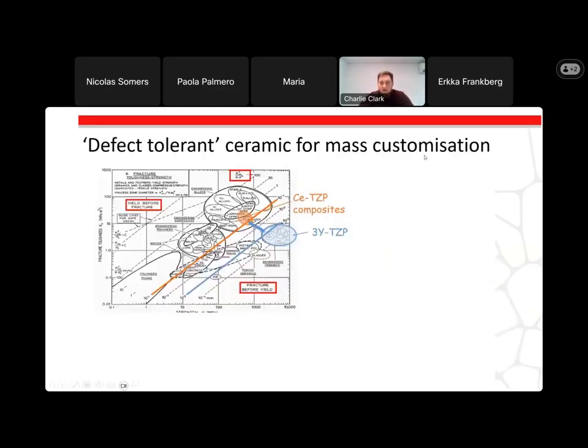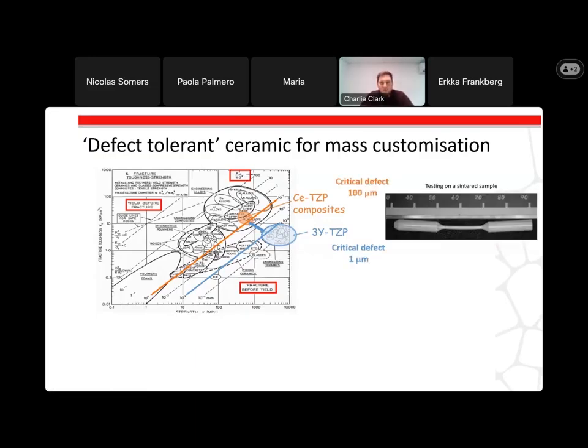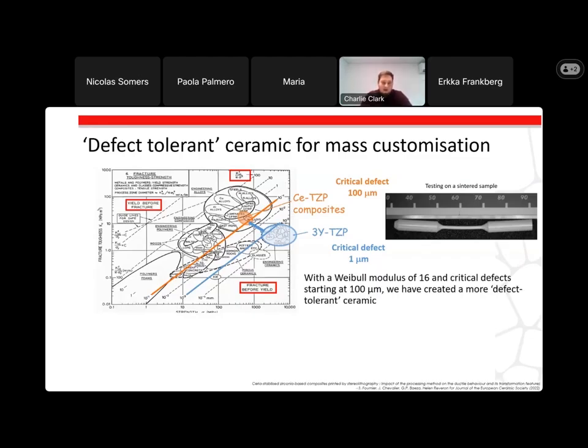But when we look at the defects, the tolerance towards defects that ceramics have, with classic zirconia stabilized with 3% yttria, we have a critical defect of 1 micron. With this new composite, we had a critical defect of 100 microns, which meant, as we can see on this sintered sample here, there was a certain flexibility that the part was able to have before breakage. So having a Weibull modulus of 16 and critical defects starting at 100 microns meant that a more defect tolerant ceramic was made.